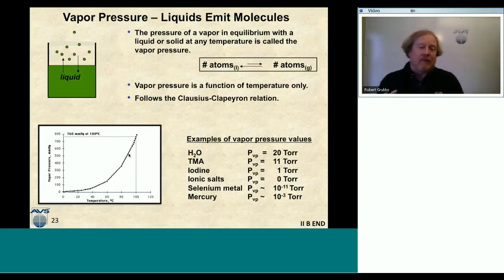And this is very important because when we talk about liquid precursors and solid precursors, we're really going to need to manipulate the vapor pressure in order to get some of these precursor molecules into the gas phase and then into our reactor. The vapor pressure is defined by the Clausius-Clapeyron relationship, which is in a PChem text. Down below I have some examples of vapor pressures. Water has a vapor pressure of 20 torr. Trimethyl aluminum, TMA, has a vapor pressure of 11 torr. This is very important because those are the two chemical precursors used in alumina ALD.